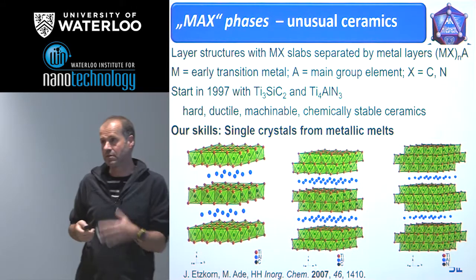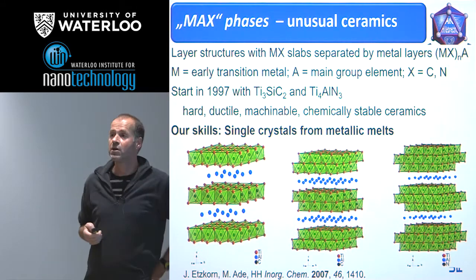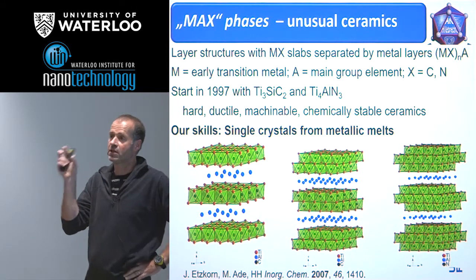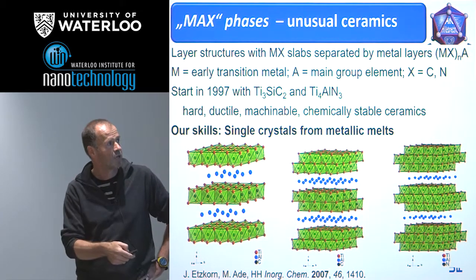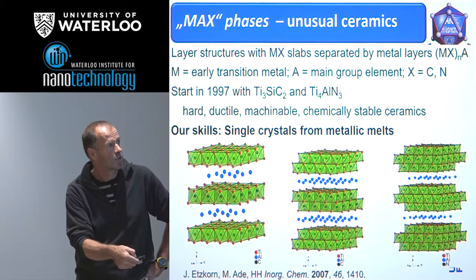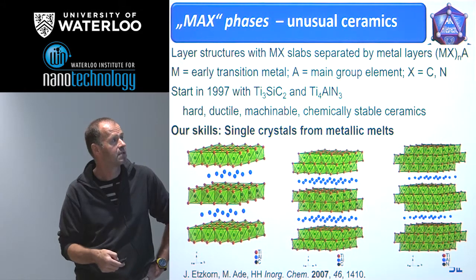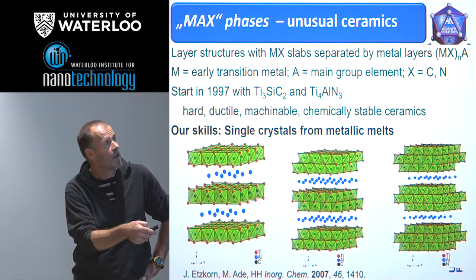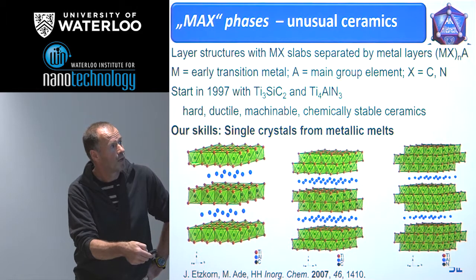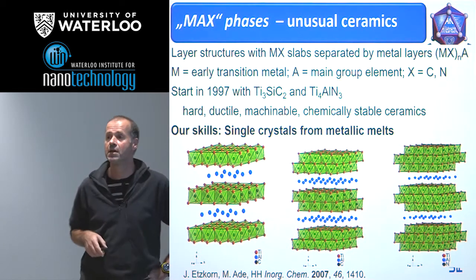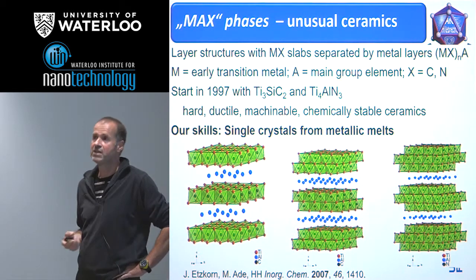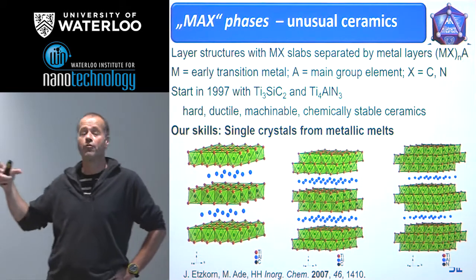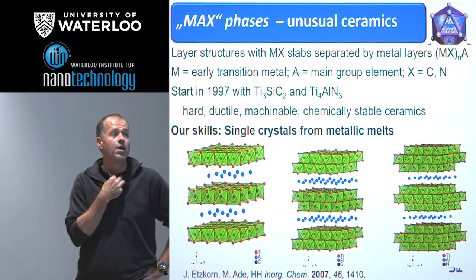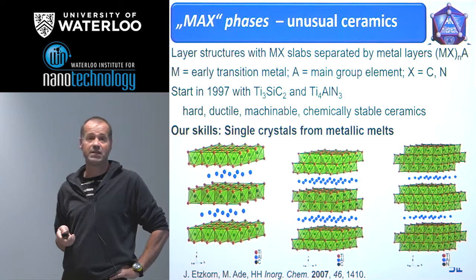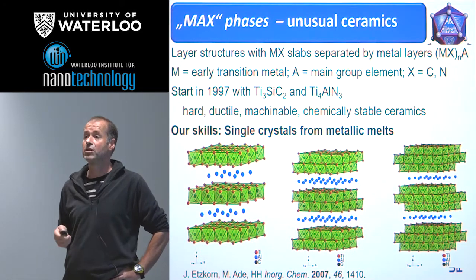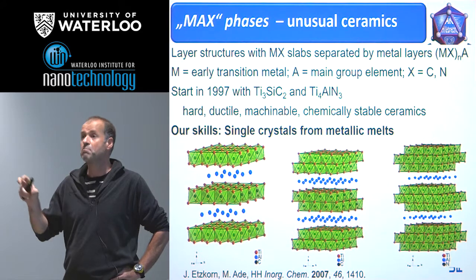And the explanation is quite simple, because you have both structural units within the crystal structure. You have one part which is a transition metal carbide part, this is M and X, and you have one part which is an intermetallic part. And so we have a quite good explanation why we have a combination of both properties. So these ceramics were investigated in a very, very extended way for the use as ceramic material.